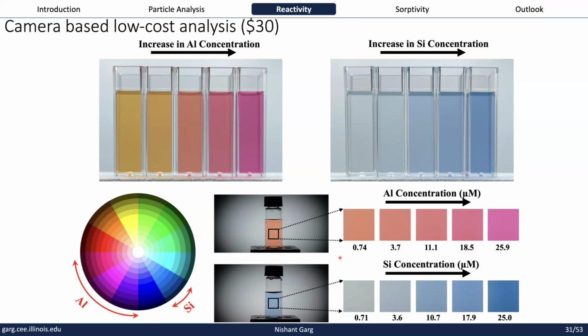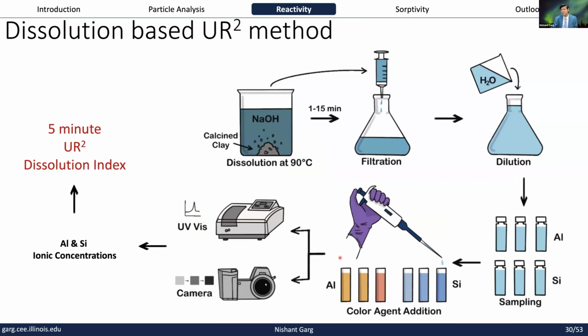There is also a question from Juliana. Some phases are more sensitive to temperature than others. How do you account for this in a test run at 90°C? This is a great question, and it goes to the whole assumption of this test. The reason we have this very aggressive condition is just to accelerate the dissolution. Now, some phases will dissolve more, some phases will dissolve less.